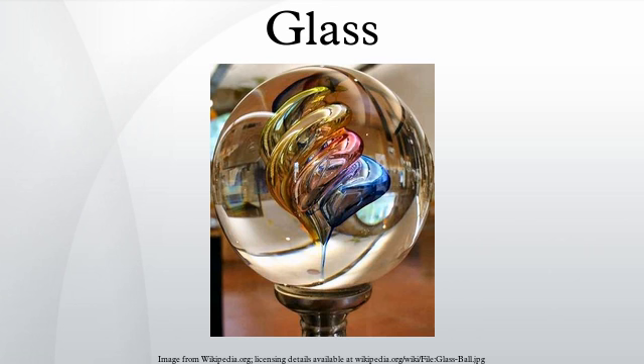Flat glass for windows and similar applications is formed by the float glass process, developed between 1953 and 1957 by Sir Alastair Pilkington and Kenneth Bickerstaff of the UK's Pilkington Brothers, who created a continuous ribbon of glass using a molten tin bath on which the molten glass flows unhindered under the influence of gravity. The top surface of the glass is subjected to nitrogen under pressure to obtain a polished finish.